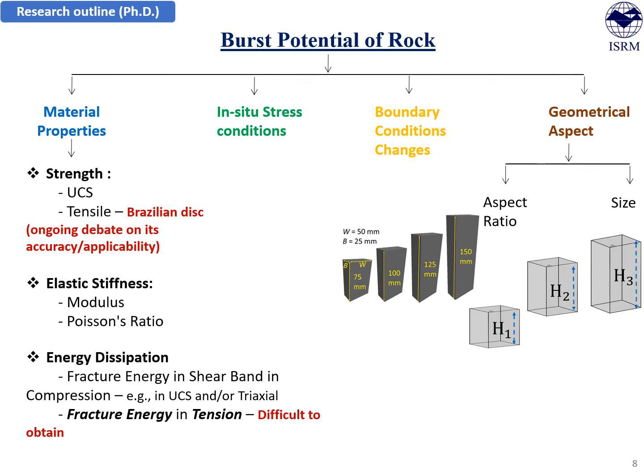And the specimen size as well. That means as we keep increasing the size of the specimen, what effect we can get on the burst potential of rock. So these factors have to be taken into account when we calculate the burst potential of rock, because in underground in situ scenarios, the size of rock is beyond our control. It is governed by in situ discontinuities, which is very difficult to capture for each and every cut in underground mining scenarios, when we take cuts in drives and when we fire stopes.